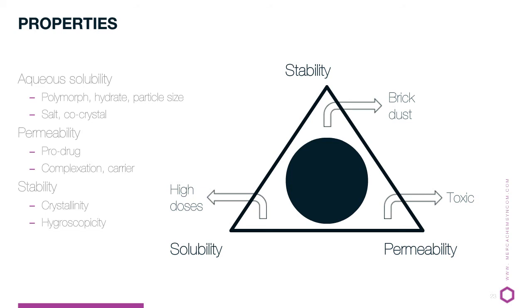Stability: looking at crystallinity, and most of the time also particle size and amorphous content. To lower hygroscopicity, you can select a different counter-ion that on its own is not hygroscopic. And the selection of the less hygroscopic material is also very important in this case.